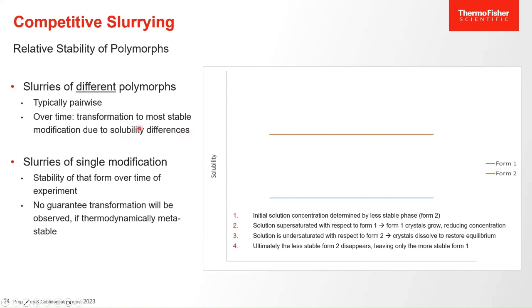Why is this? The most stable form has the lowest solubility, as indicated in the diagram here. The less stable form has a higher solubility. The concentration in your initial solution will be determined by the less stable phase, so it will be up here. But that means that the more stable phase is supersaturated and will start to grow. This means a reduction in concentration in solution, and in turn, the less stable phase starts to dissolve to restore equilibrium, and ultimately, the less stable form disappears, leaving only the most stable form.